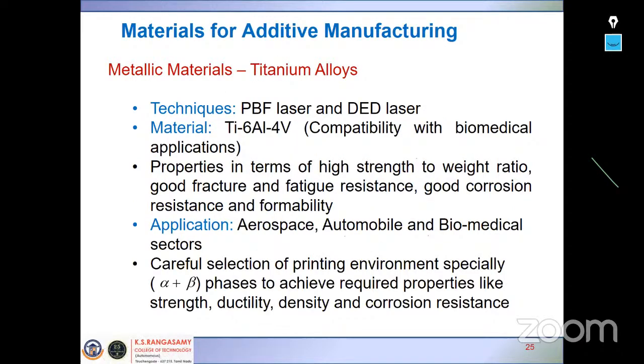And the titanium alloys. Again, the powder bed fusion method and the direct energy deposition method are used for fabricating titanium-based 3D printed material. The most commonly used material is Ti6Al4V, and it is compatible with biomedical applications. All the implants can be fabricated using this titanium alloy, and it is commonly used in biomedical applications due to its compatibility with tissues. The properties are a high strength-to-weight ratio, good fracture and fatigue resistance, and good corrosion resistance and formability. Because of these properties, titanium alloys are used for biomedical and other applications.